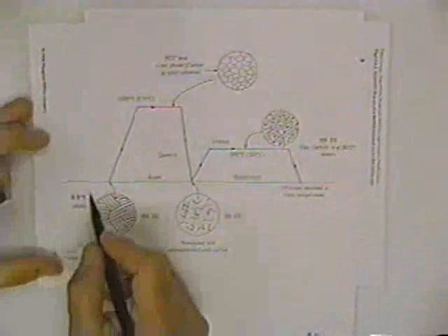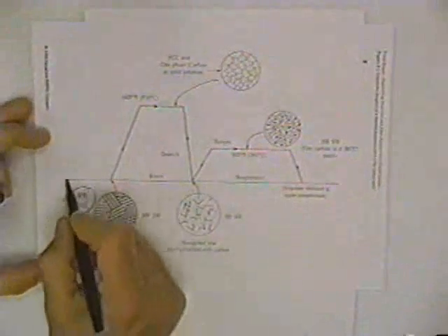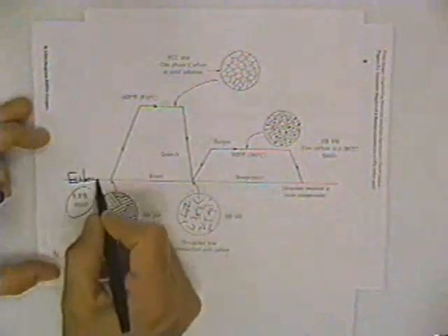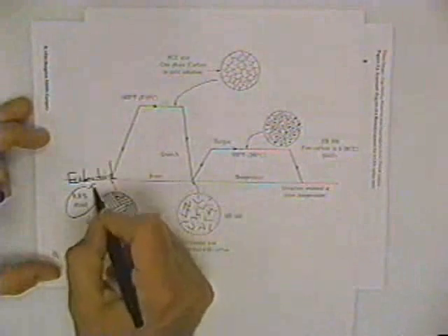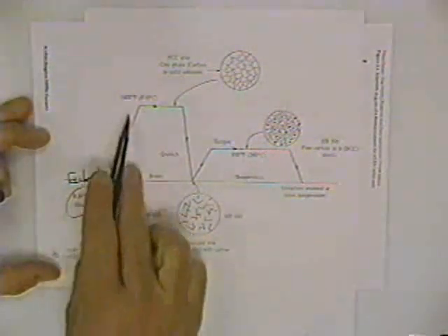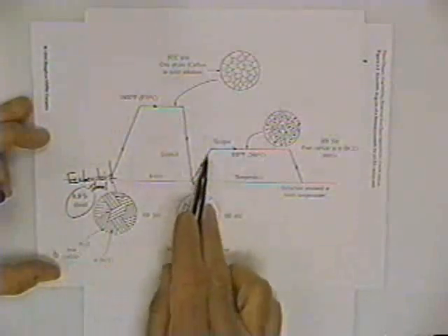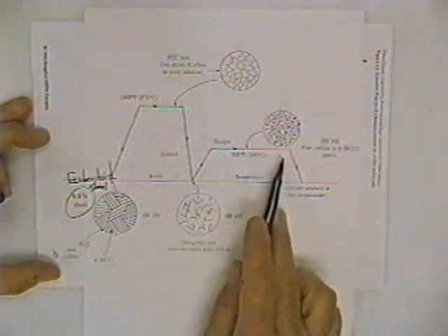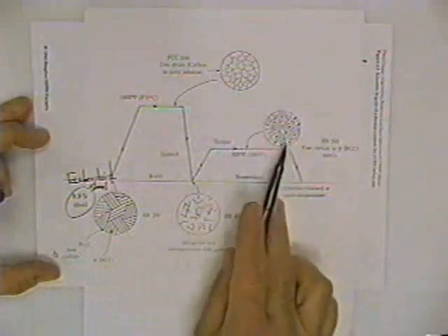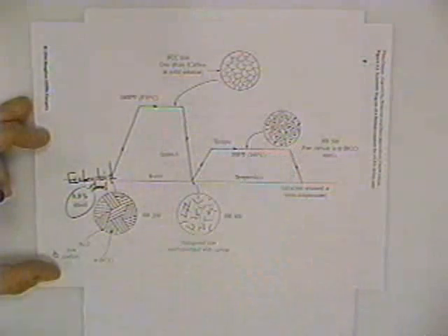If you look on page 27, you will see a heat treatment cycle for a 0.8% steel. This is called a eutectoid steel. You heat it up to 1600, hold it till the alloying elements are in solution, quench it to room temperature, reheat it to 500, hold it, and the phases will redistribute so that they increase the ductility and still have reasonable strength.